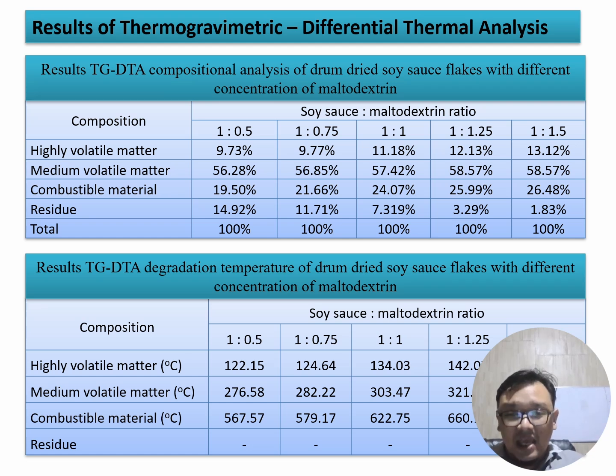So we see that as it increases, the maltodextrin protects or encapsulates the volatile material, but there are certain changes in the residual that may affect the salt content or the mineral as well as the protein of our materials. In the second table, we also saw that as the soy sauce and the maltodextrin increase, the temperature required for the volatile materials also increases. We saw that as it increases, the temperature in terms of degradation also increases. We saw that the combustion of our material also increases because of the presence of carbohydrate in our maltodextrin.